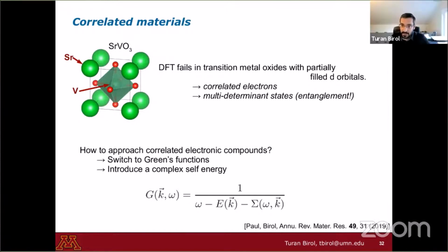That's a great question. And the short answer is no, because the semiconductor band gaps are underestimated due to things like long-range exchange, etc., that is not added in the type of DMFT that I'm using. In transition metals, the Mott insulating phases are often predicted to be metals by DFT. So DMFT can correct that because that is due to the local physics on a single transition atom. But the semiconductor band gap problem would not be solved by DMFT. There are other approaches like GW or HSE and so on, where people try to correct those band gaps. But DMFT would be the wrong tool for that.